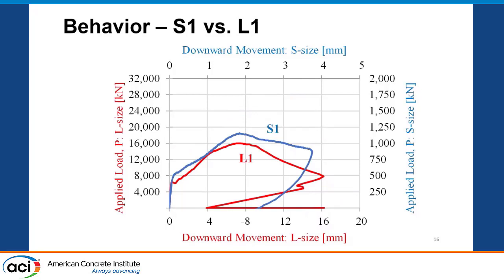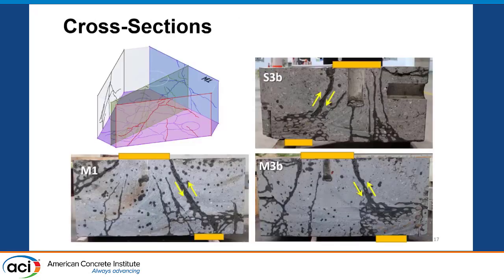In the single-layered specimens, it was really a similar story. Obviously, they reached lower strength than the triple-layered specimens, but we saw a similar phenomenon: cracking at approximately similar time, lower peak strength, and then also different post-cracking stiffness for the largest specimen versus the smallest specimen. I'm not going to get into detail about this, but this is the result from our saw cutting assessment, which I thought was relatively interesting.